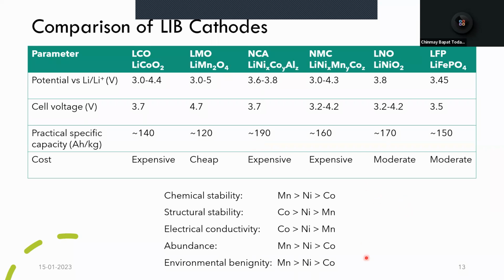When it comes to the use of these particular transition elements with respect to these parameters, we see that nickel lies in the middle for all these parameters, and cobalt and manganese lie on the opposite ends. Since cobalt is expensive and toxic, more recently increasing nickel content and eliminating cobalt content is becoming prominent. However, there are three major problems when it comes to increasing nickel content. That is cyclic instability, thermal instability, and sensitivity when it comes in contact with air. High nickel-based cathodes also suffer from cracks during charging and discharging, and it exaggerates the surface reactivity, due to which there is a higher chance of metal dissolution into the electrolyte and rapid capacity fade as the cycling progresses. Therefore, it is important to optimize the manganese and nickel content while still keeping some sort of cobalt content to keep the cell stable.